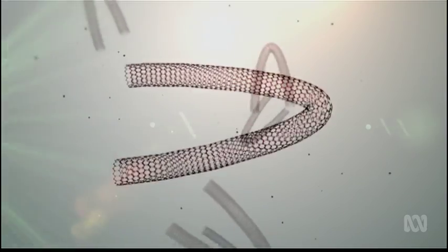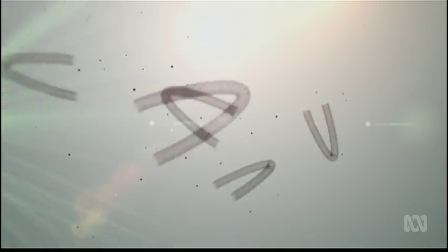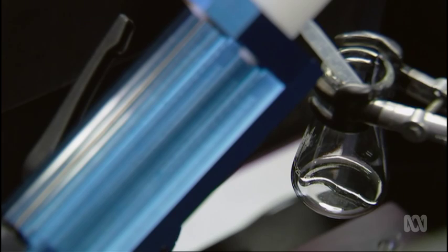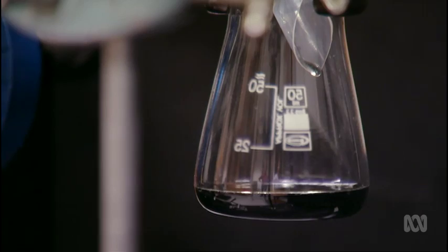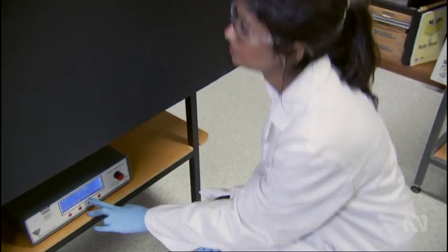Using a high-powered laser, Casturi was able to cut the nanotubes as they randomly passed in front of a beam, at the exact point where the intense spinning had bent them. It's essentially like taking scissors and chopping at a nanoscale level. The combination of the laser and the vortex fluidic device could cut the nanotubes into the required lengths.